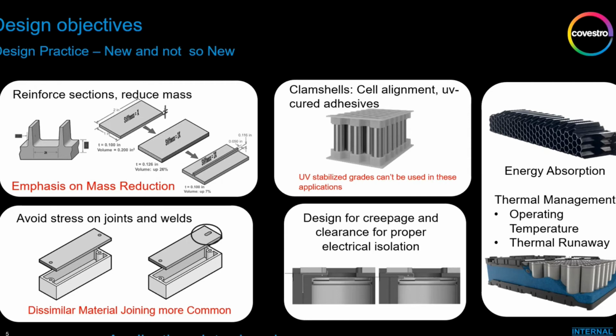Some other things, again, there's some new and not so new things that you need to think about, or I should say are related more to battery applications. For example, energy density. Energy density is a huge factor for batteries. You want to get the most kilowatt hours per kilogram that you can out of a battery design. So what does that mean? It means mass reduction. You can either increase the output of your batteries, which is more kilowatt hours, or you can reduce the weight of the assembly, which is reducing the kilograms, so you can get your kilowatt hours per kilogram higher. To do that, we can incorporate design features and get mass reduction by smart design, by creating a structure that gives you the stiffness that you need while reducing the amount of material you need to get there.